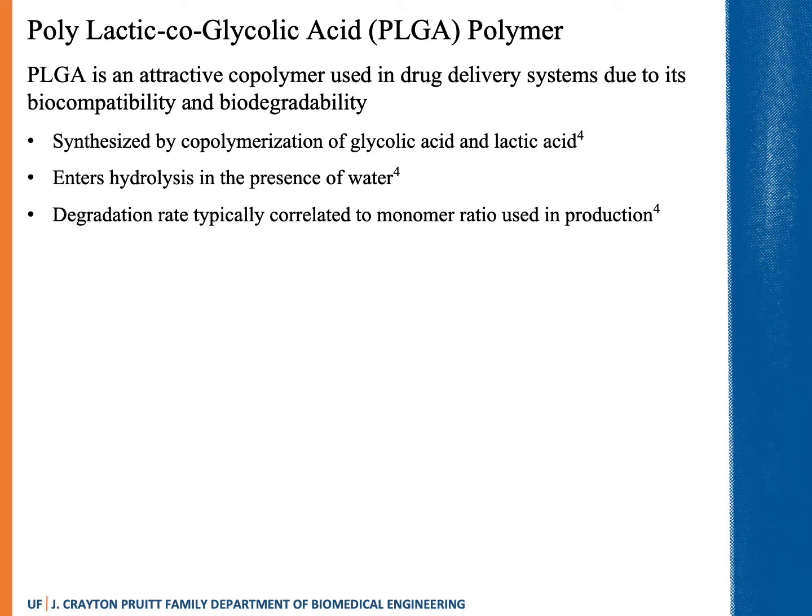Degradation rates typically are correlated to the monomer ratio used in production. Higher content of glycolide units lead to a lower degradation time. We want that lower time because as soon as an injury happens, we want to be able to protect the cartilage as quickly as possible.